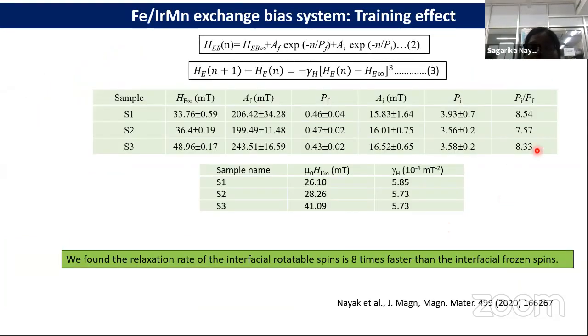In this slide, you can see this ratio of pi by pf that we calculate from equation 2, where pi is the relaxation rate of the rotatable spin and pf is the relaxation rate of the frozen spins, and f is the magnitude weight factor of frozen spins, and a is the weight factor of rotatable spins. We found the magnitude of this weight factor of frozen spins is higher than the weight factor of rotatable spins.